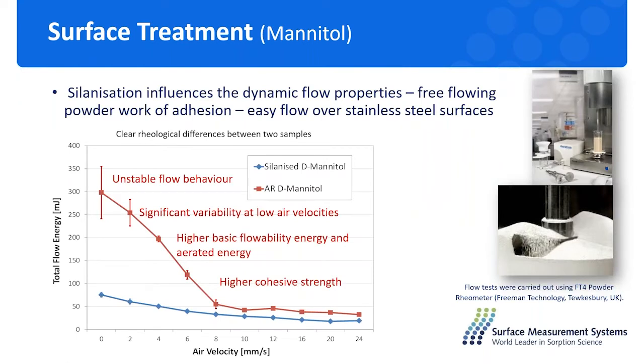And then we proved our prediction with some flowability tests of the same mannitol. We find that the treated D-mannitol is hardly changing with the air flow velocity, while the untreated mannitol has quite unstable flow behavior at low air velocity and shows significant variability at low air velocity. So basically, the flowability behavior of different kinds of particles could be related to the surface energy and also the surface energy distribution of that particle itself, by calculating the work of cohesion as a parameter to predict the flowability behavior of the particle itself.